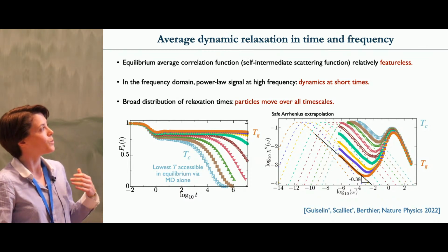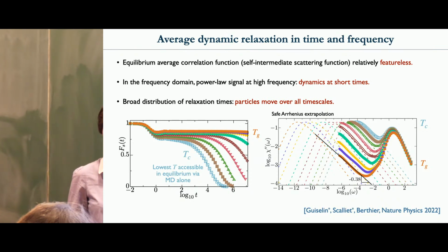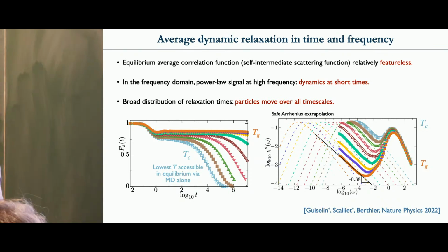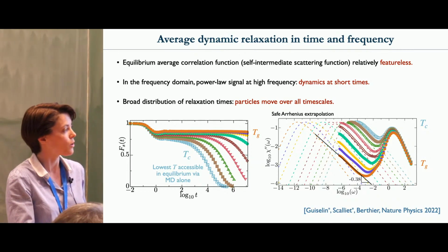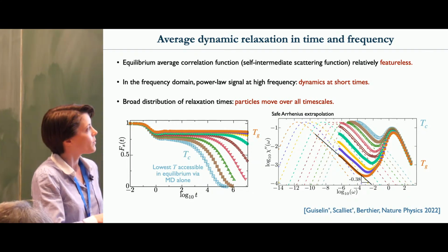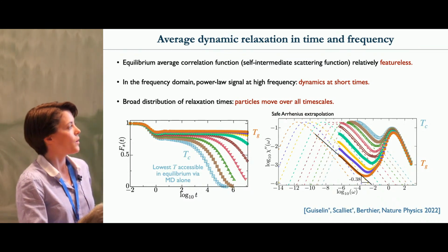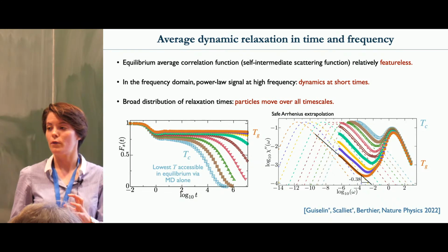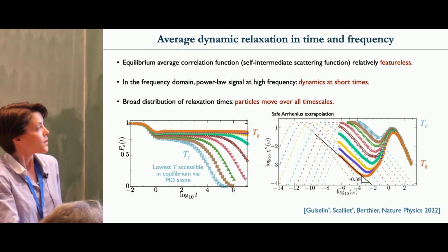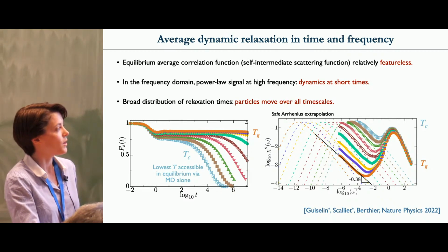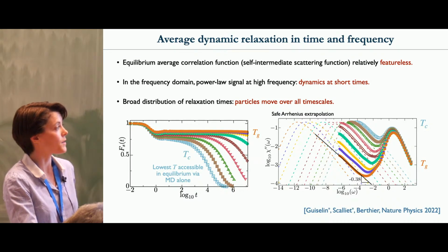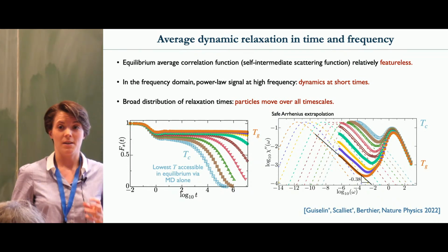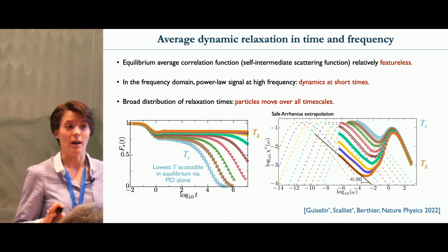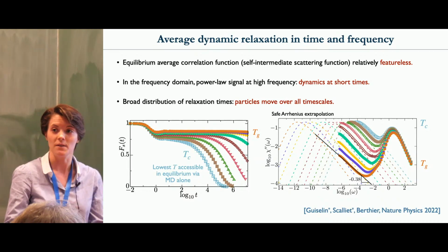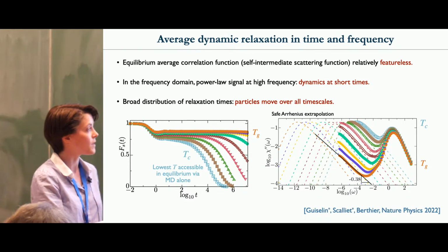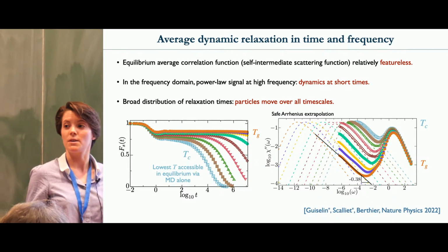But actually, if you go to another type of description that is used mostly by experimentalists, they compute what's called a dynamic susceptibility. So now this is in terms of frequency ranges, with here short times and here long times. You transform this data into this spectrum that basically tells you the amplitude is correlated to the amount of particles that are moving at a given time scale or frequency scale. All right. So what you see here is that going to lower temperatures and going especially to the experimental glass transition, what you have here is a signal. We actually fit it well by a power law. And what this is telling you is that while here you have the feeling that nothing is happening at all, what you have is a signal. It's low in amplitude, so it means that a few particles are moving. But it still means that what you have in the system is a broad distribution of timescales or frequencies over which particles are moving.